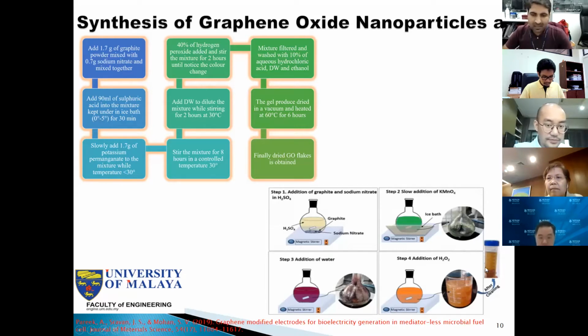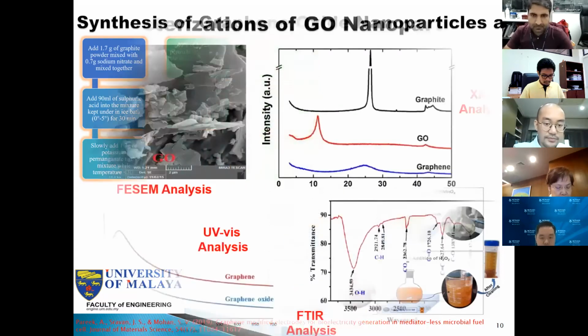And it's really difficult to wash the graphene. So basically the most important step is the washing of the graphene. After washing, we got it in powder form. Then from that refined powder we can disperse it in water and make the nanofluid according to our required weight percent concentrations.